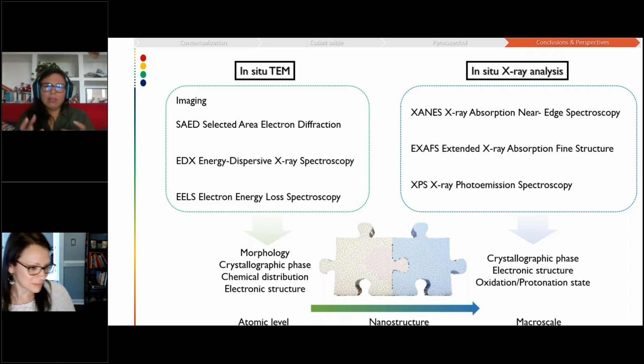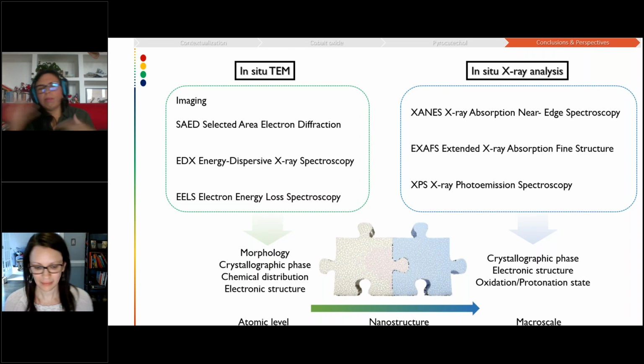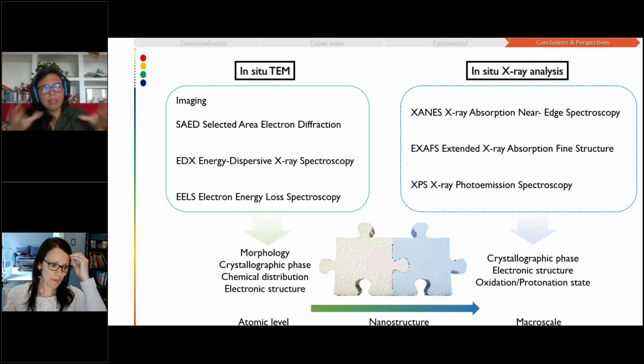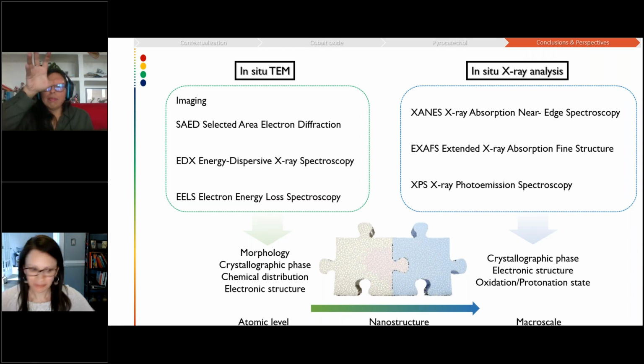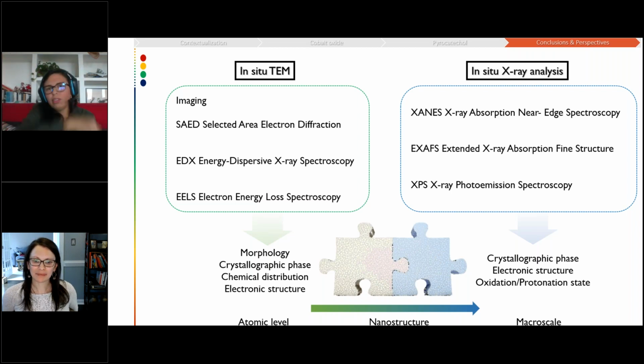Well, it is difficult to say the same electron flux density, because TEM has a parallel beam while STEM has a convergent beam. But it is in the same area, that's for sure, because we did the experiment in STEM, and then we passed to TEM, keeping it in the same place, and we just switched the mode and did the measurement. About the electron dose, I think that for TEM it will be higher for sure, but it would be interesting to keep it as low as possible to be able to compare with STEM. Probably, sure, we didn't think of that at that time.